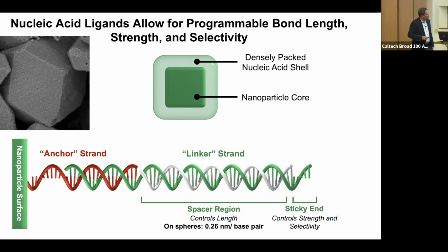And then this is key. This is a sticky end. In the early days, we used what we thought we needed, long sticky ends, because we thought we needed enough of an interaction to bring these together. But that's amplified, that's magnified, especially as you get bigger and bigger particles, because you get cooperativity. So you actually don't want long overlaps because you get stuck in kinetic traps.